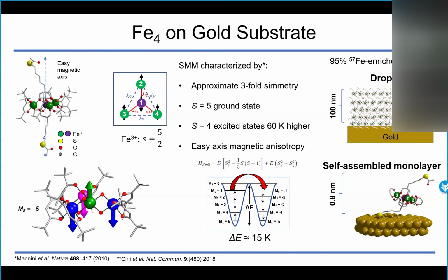What we wanted to study was a single molecule magnet called iron-4. The name comes from the fact that it is composed of 4 iron ions. 3 are at the vertices of an approximately equilateral triangle, and 1 is in the center. They are antiferromagnetically coupled, such that the result is a total spin ground state with S equal 5. The molecules were enriched in iron-57, and then they were deposited on a gold substrate. 2 samples were synthesized, a dropcast one, so a very thick one, 100 nanometers of molecule, and a self-assembled monolayer, which means just one layer of molecules less than 1 nanometer on gold.